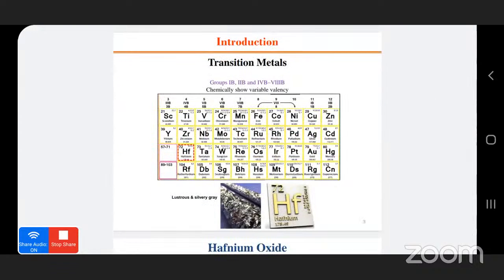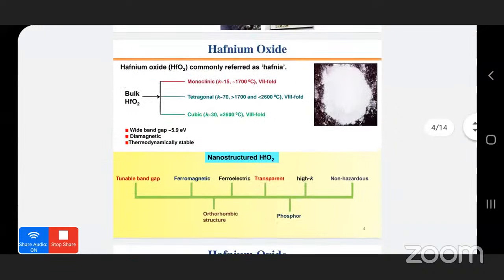So hafnium is basically a transition metal having an atomic number of 72. Its physical appearance is lustrous and silvery gray in color. Hafnium oxide is commonly referred to as hafnia. Bulk hafnia shows polymorphism. It has three different structures depending on the temperature. The most stable phase of hafnium oxide is monoclinic, which has a dielectric constant of 15. This monoclinic phase is stable up to a temperature of 1700 degrees Celsius, and it is a seven-fold coordinated system.